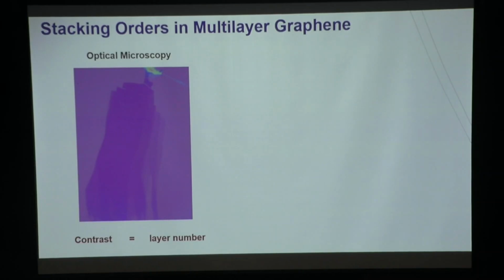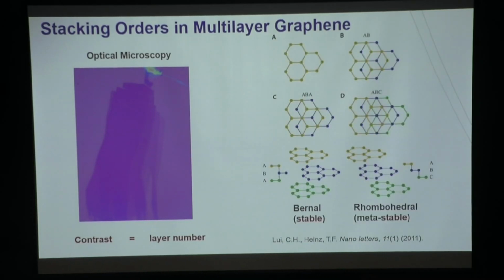Okay, that's good. However, not many people appreciate that even within the region that has a homogeneous layer number, there could be subtleties about how the layers of carbon are stacked on top of each other. If you have monolayer graphene, it's always like this. If you have bilayer graphene, in the stable form, it's always a so-called A-B stacking. But if you go beyond 2 layers, get into 3 layers, you have to decide whether to shift the 3rd layer to the left or the right with respect to the first 2 layers. And that will give you these 2 different stacking orders.